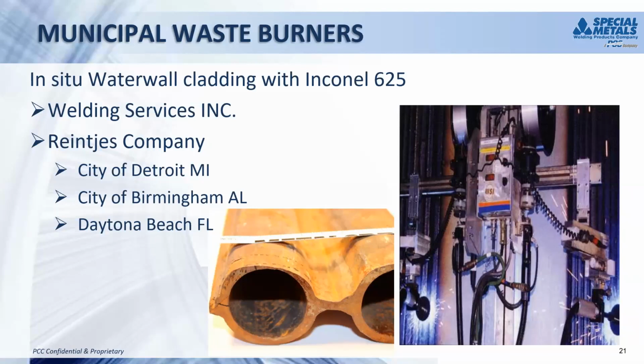Where that's commonly done in a vertical down MIG process, as you can see the piece of equipment on the right, which is a very quick weave back and forth vertical down to just cover, but a very thin layer of nickel over that alloyed steel, which just really gives it substantially better corrosion protection. Next slide.